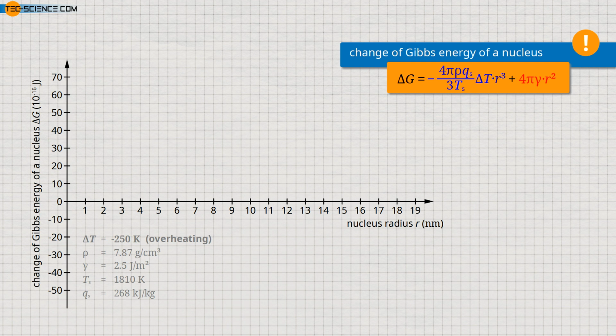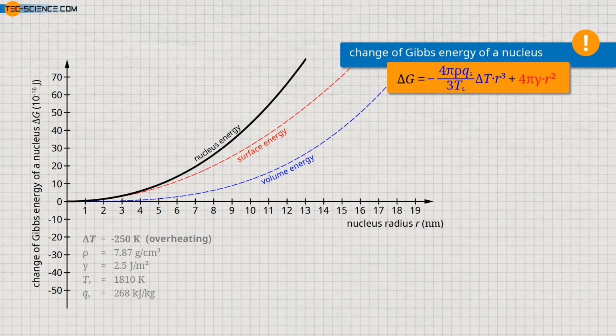For temperatures above the solidification point, the supercooling is mathematically negative and thus both terms are positive. While in this case the term marked in red for the surface energy increases with the square of the nucleus radius, the term marked in blue for the volume energy increases with the third power of the nucleus radius. For this case, the diagram shows the change in Gibbs energy for the nucleus as the sum of the two terms with increasing radius. In any case, the Gibbs energy of the nucleus will increase. Consequently, a stable thermodynamic equilibrium between the solidified nucleus and the rest of the melt will not be established.